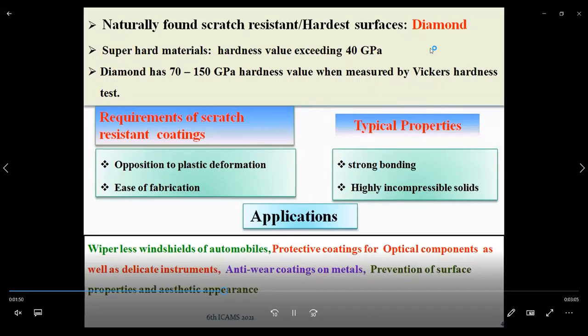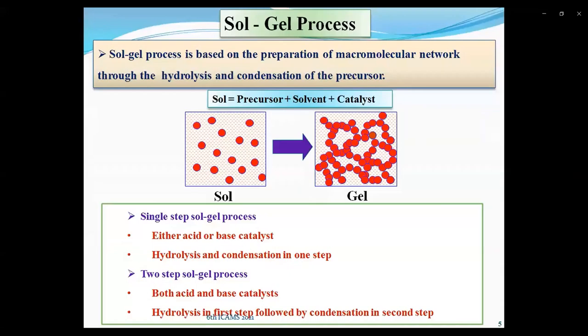These coatings are prepared with the help of the sol-gel process. The sol-gel process is based on the preparation of a macromolecular network through the hydrolysis and condensation of the precursor. Sol is equal to precursor plus solvent plus catalyst, and the diagrammatical representation of sol and gel is as shown in the diagram. This process has two stages, that is single step sol-gel process and two step sol-gel process. The details are elsewhere.